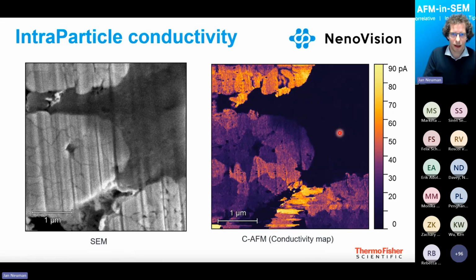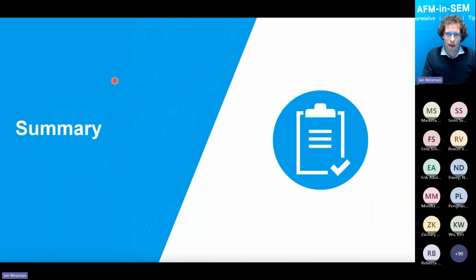You can correlate it with the SEM again, and even more, you can highlight another interesting feature. For example, conductivity in areas which should not be conductive, which we do not see in the SEM, etc. So, a very powerful technique. With that, conductivity mapping can help you to reveal the differences in individual primary particles.